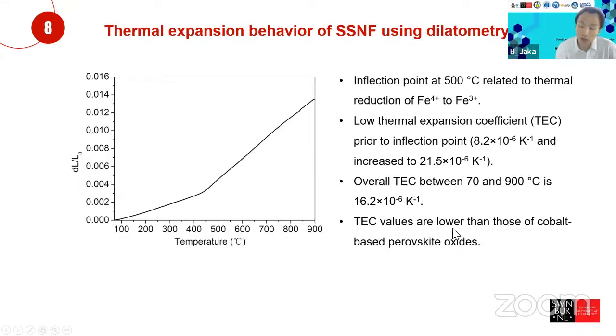And of course, these TEC values are lower compared to the cobalt perovskite oxides because, like I told you again, the performance of the cathode component is tightly related to stability. So if you have a lower thermal expansion coefficient, then you will have lower expansion as you heat up, and that will affect the mechanical integrity of your solid oxide fuel cell.